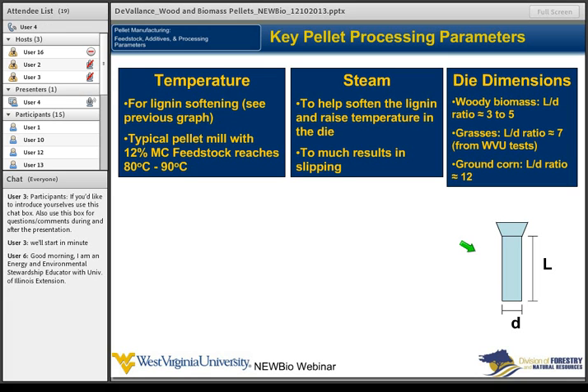In terms of the dies themselves, we have this chamfered area where the material is going to flow into, and we really don't start doing anything in terms of compression until we start getting material through here. So we look at the length to diameter, or L over D ratio, of your die. So you can put different thicknesses of dies in your process. And for woody biomass, we're looking at a range from 3 to 5. Grasses, about 7, and ground corn, they recommend about 12.